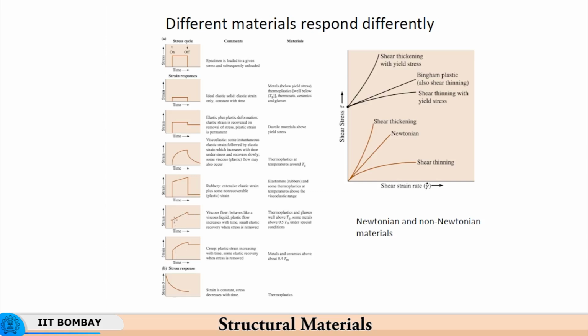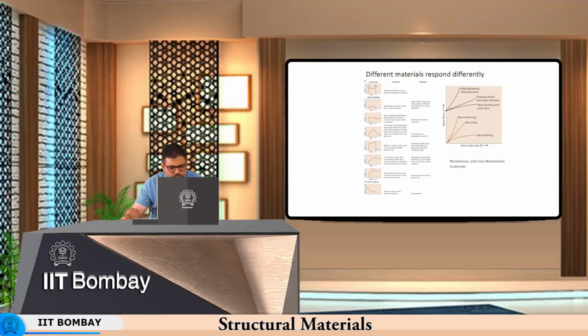Here the only difference is that this is linear. In the case of viscous flow there is a linear increase in strain with constant stress, whereas here there is a non-linear increase in strain with constant stress. So, you have creep plastic strain increasing with time and then after some elastic recovery. Both are similar, because even in creep there are viscous effects, there is some amount of grain boundary sliding, there is dislocation activity also inside the material, and therefore, for the same stimulus you have a different response of the material in terms of strain.